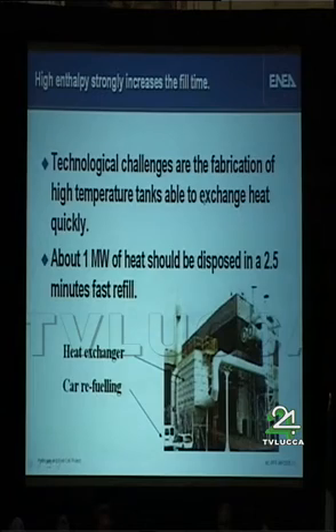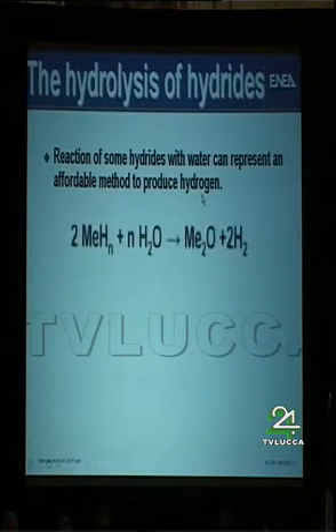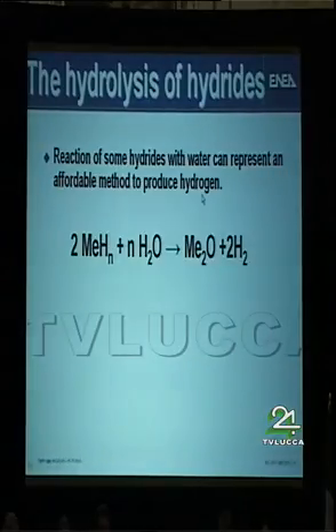Technological challenges are the fabrication of high-temperature tanks working at about 300 degrees, able to exchange heat very quickly. About 1 megawatt of heat should be disposed of in 2.5 minutes for a fast refill. This is a picture showing a car refueling very fast and a heat exchanger in the back to remove the heat.